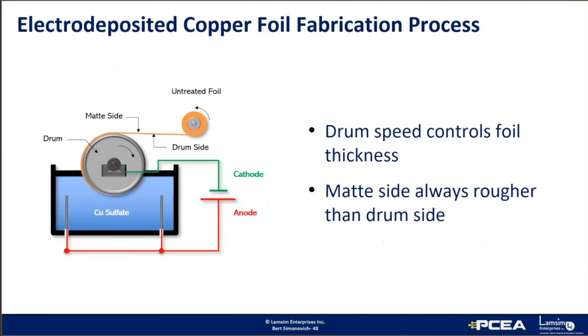To better understand conductor roughness, I will start with the electrodeposited copper foil fabrication process. A large drum made of titanium or stainless steel is partially submerged into a vat of copper sulfate solution. An electric potential is applied between the drum, the cathode, and the solution. As the drum slowly rotates, copper is electro-deposited onto it. The thickness of the foil is controlled by the speed of the drum. The important takeaway from this slide is to note the drum side and the matte side of the foil. The matte side is the side facing the solution, while the drum side is the side contacting the drum. The drum side of the foil is always smoother than the matte side.